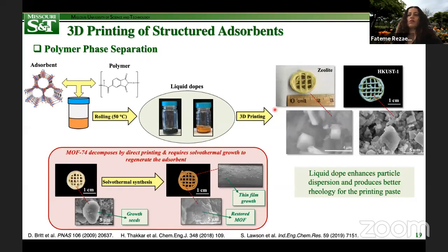However, for some other MOFs, such as MOF-74, the dope formation decomposed the MOF particles. And this method failed to make any MOF monolith using polymer phase separation. Nevertheless, we used these decomposed particles as growth seeds to generate a film on the surface. So these are seed growths for the decomposed MOF-74.